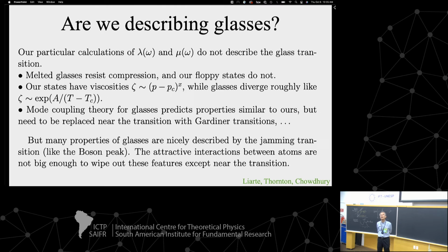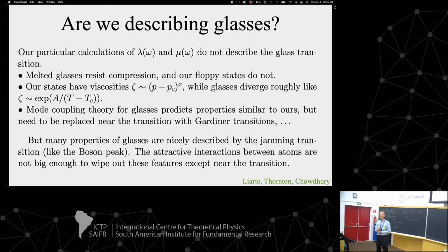Now, I'm not guaranteeing you, I have this feeling. Does the viscosity diverge in the Gardner phase? Maybe I will comment at the end. So what we did is that we computed the moduli across the glass phase, and what happens is that when you cross this Gardner transition, they stay finite.